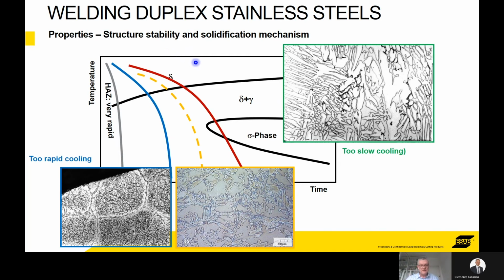The more time taken, and as you cross these lines, this illustrates the phases that are going to be precipitated into the molten metal. So if you take too long to cool down, then you will dwell. There will be portions of the weld that will be at these temperatures for an extended period of time, and that creates problems. It precipitates these intermetallic phases in the metal.